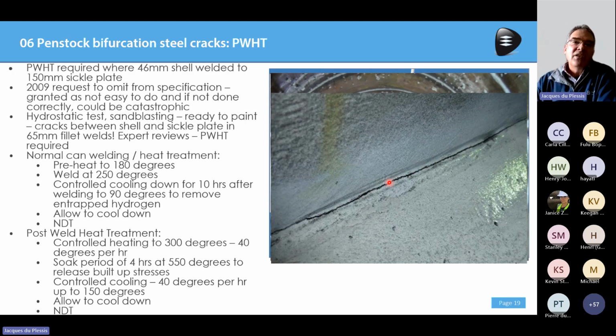So everything was done. The weld tests were done. Everything looked fine. The contractor did his sandblasting, and everything was ready to paint. And our inspectors picked up this crack in the weld. That's a 65 millimeter fillet weld. And then to just take one step backwards, the specifications originally included post-weld heat treatment. But post-weld heat treatment is not easy to get right. And if you mess it up, you actually change the material properties.